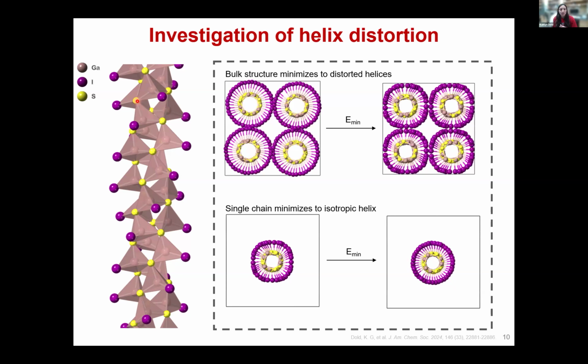From the DFT calculations, we found that if we take the bulk structure of circular cross sections and do an energy minimization calculation, we end up with the squircular distorted cross sections. However, if we take a single chain in a vacuum of the squircular cross section and energy minimize it, we end up with an isotropic cross section. So this really told us that the origin of this distortion has to do with the interchain van der Waals interactions, and that these interactions between chains play a major role in the crystal structure and packing of these materials.